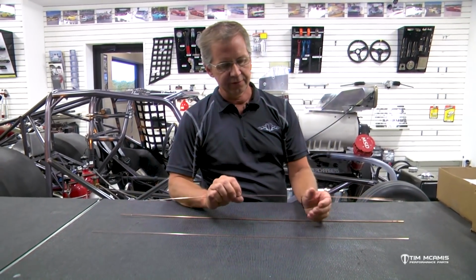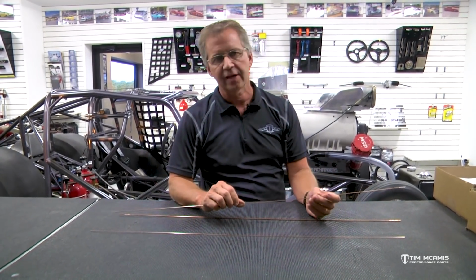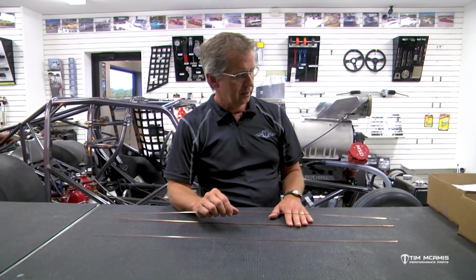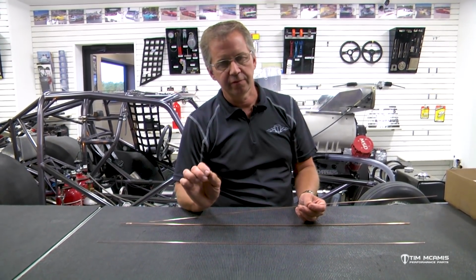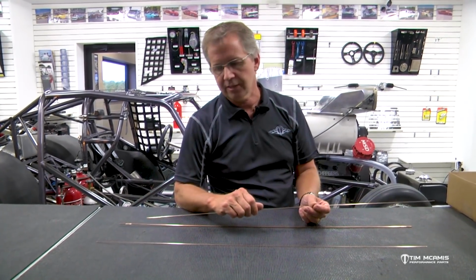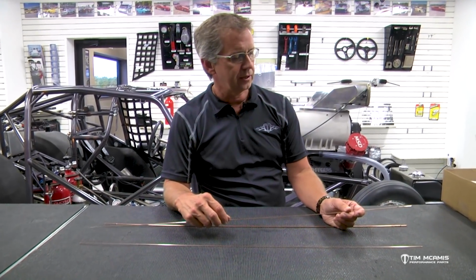The chassis stuff, the 1/16 is a nice size for that, for a decent fit. Not quite as good of a fit, you can use 3/32, or if you're actually welding some heavier wall tube together where you're welding like .083 to .083, you might want to use a little more heat and use a 3/32 rod, because you want the weld puddle not to be too big, but you don't want it to be concave either. You want to have enough filler material on there so that you've got a nice weld bead structure that's going to fill that joint nicely. So the 70 material is going to be used for all general welding on the chassis.